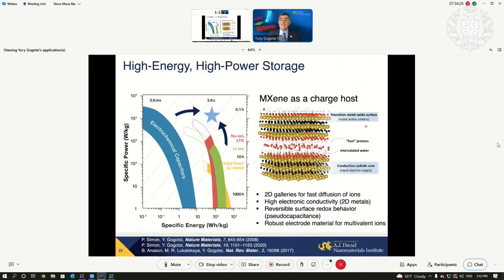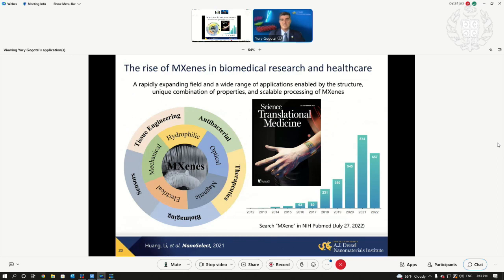If we have highly conducting materials with electronic conductivity, unlike current battery materials, but with the ability of redox reaction storage, using transition metals like molybdenum, titanium, niobium, vanadium, the same as in lithium-ion batteries, plus ionic transport and no solid-state diffusion, since 2D materials are all surface, we may finally have really high-rate, high-power storage devices.